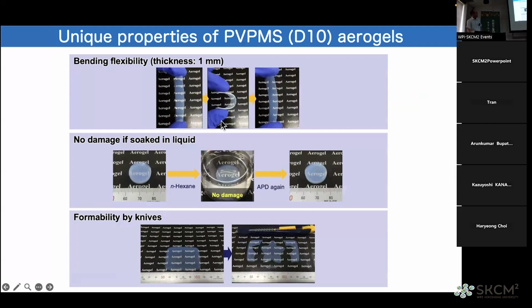And when we prepare thinner ones, like 1 millimeter thickness, it is bendable like this. And also very tough, so we can put the once dried gel into a liquid again, and then dry it again. This is also possible now. And actually, aerogels are so friable, so it is very difficult to cut into shape with a nice technique. But with this tough material, you can see that we can cut the sheet of aerogel with a very ordinary knife into a very complex shape. Okay.